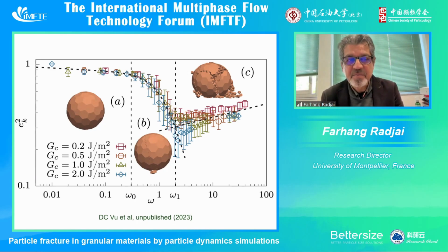Then we have a second regime where, when omega increases in this range, the restitution coefficient is decreasing because we have more and more damage of the interfaces between the fragments inside the particle. So basically, we are damaging. So the damage is increasing. And then a third regime, and that's the regime that we saw before, where the restitution coefficient increases. An interesting point is that this quantity omega does not scale this third part. It only scales the first two parts of the behavior. And that's interesting. And we find the same thing for agglomerates of wet particles, nearly the same behavior. Elastic, elastoplastic, and then damage